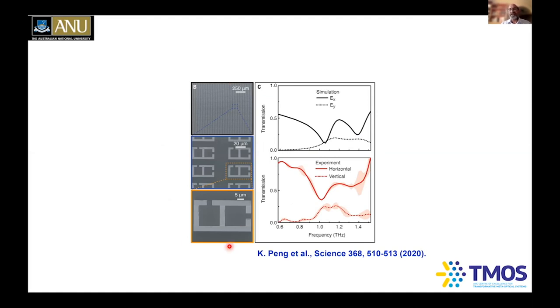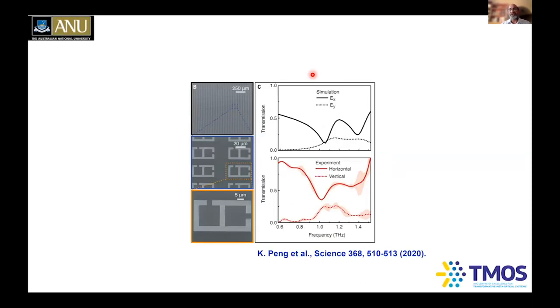So she's designed these terahertz metamaterials and fabricated these ones. And then here is the theoretically simulated horizontal polarization should have this shape, and the vertical polarization should have this shape, and the experimentally measured ones are also very much comparable to the theoretical ones, indicating that Kun Peng's 3 years of hard work really paid off.